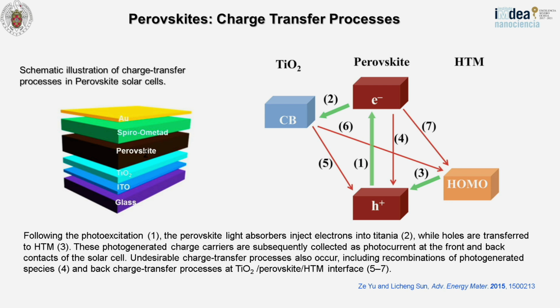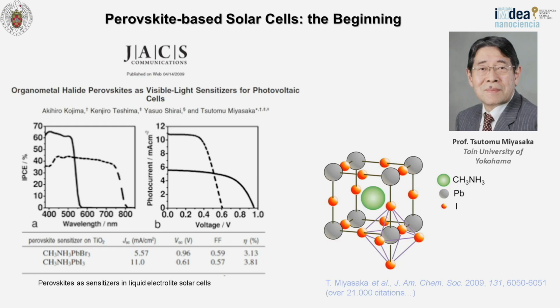From here, the perovskite injects the electrons into the titania, and at the same time, the holes are transferred to the hole transporting material. These are the green pathways, but then there are other red pathways which are negative, and this is one of the reasons why the efficiencies are lower than expected. Many of these recombination processes occur at the interlayers.